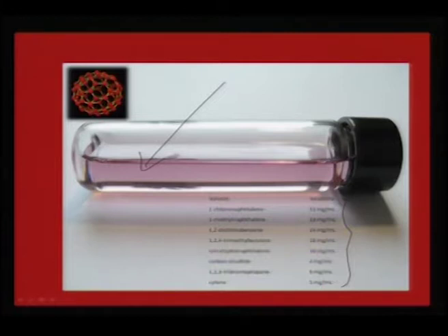and this can be used for a variety of other operations. And therefore, the solvents that we need to use whenever we get a carbon soot go in this order: naphthalene based solvents, or as you see here dichlorobenzene, trimethylbenzene, xylene, carbon disulfide. All this shows very good solvent property for this fullerene.